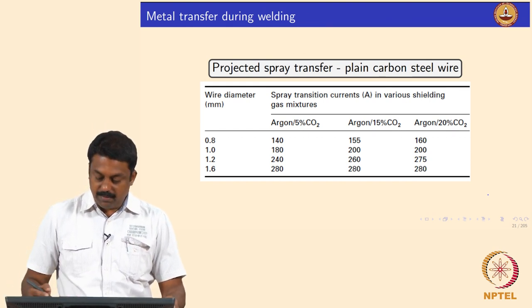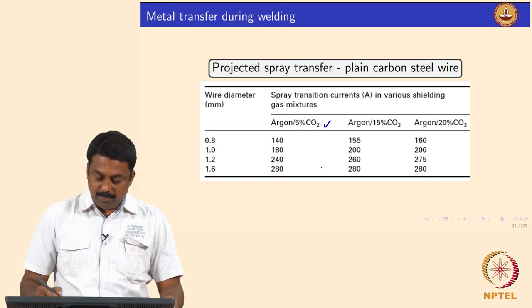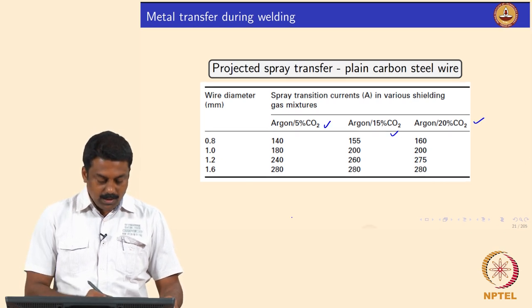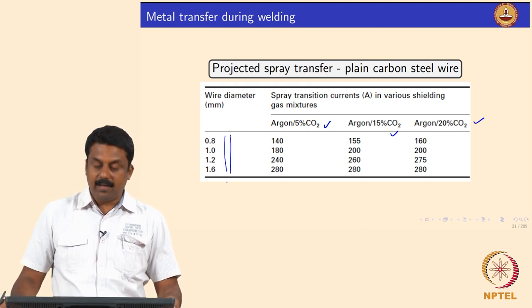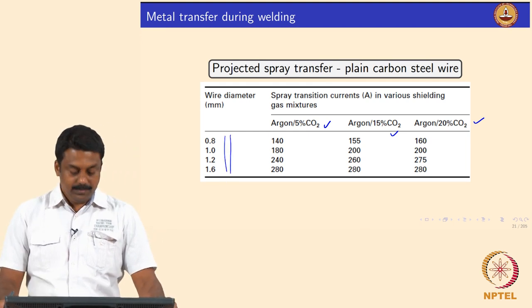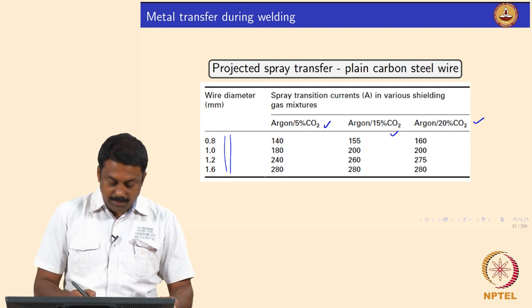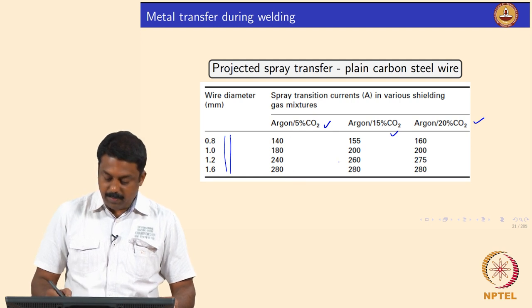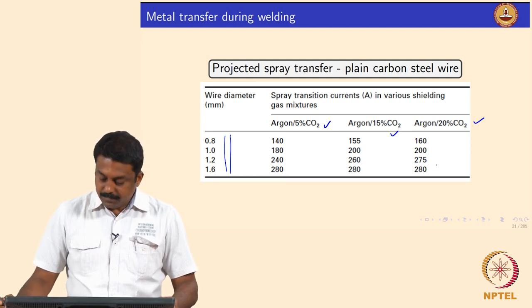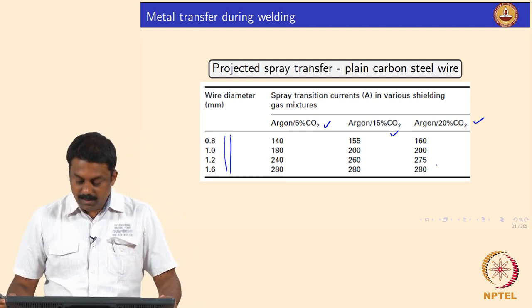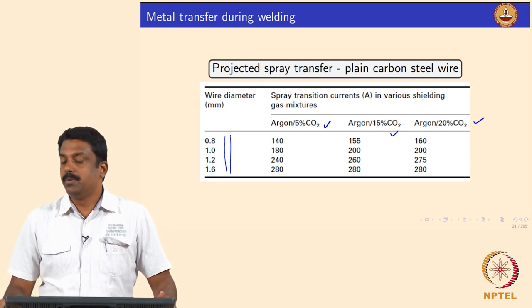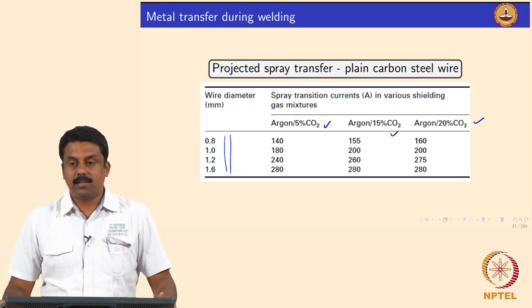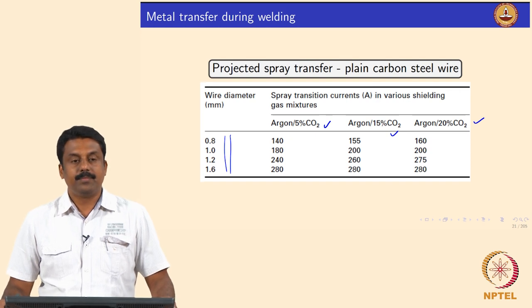Some key parameters are listed for argon plus 5% CO2, argon plus 15% CO2, and argon plus 20% CO2 for varying filler wire diameters. The spray transition current depends on these conditions — if you increase the wire diameter, the spray transition current also increases. You can identify the appropriate transition current and choose the welding current based on the desired mode of transfer.